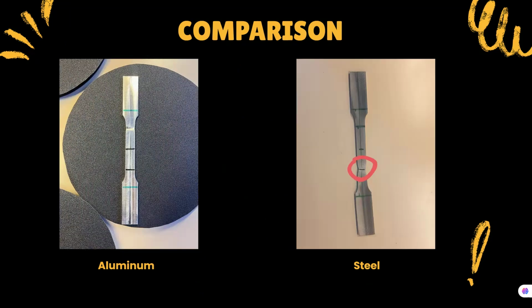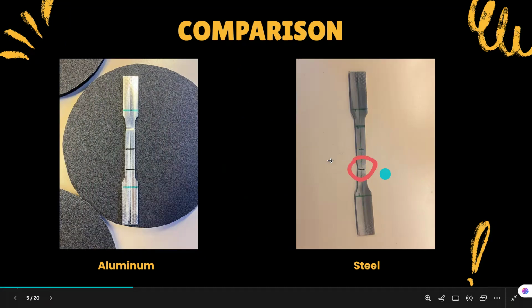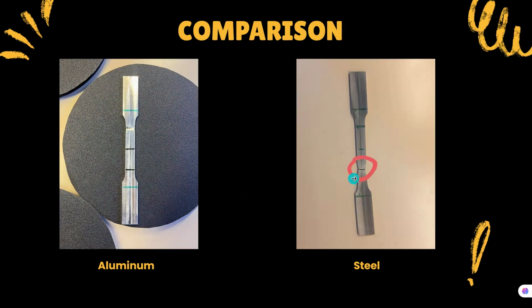Okay, so this is the result from the test for aluminum, and steel, this is for the metallic specimen. We can see there is the area of necking that I marked with a red circle, and it actually broke into two. The fracture happened in the gauge area.